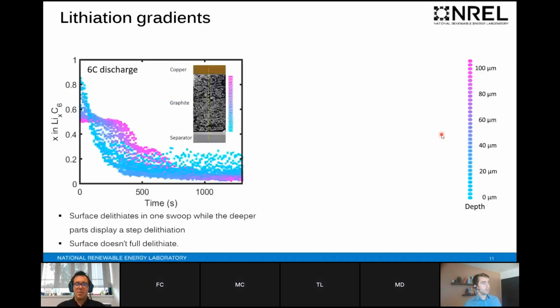The same transport limitations and lithiation gradients are observed during discharge. So this was a 6C discharge. You see very rapid reduction in state of charge close to the surface, very little response until about 400 seconds close to the current collector. And then surprisingly, we see that everywhere except the very vicinity of the surface fully delithiates. But the surface regions close to the separator don't fully delithiate despite the current being drawn.